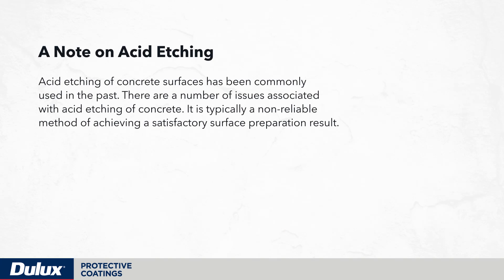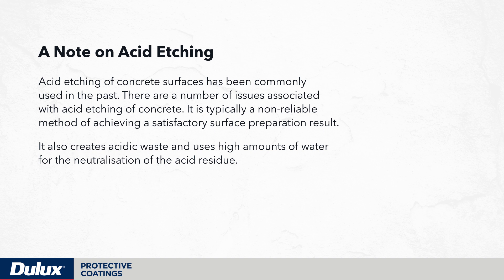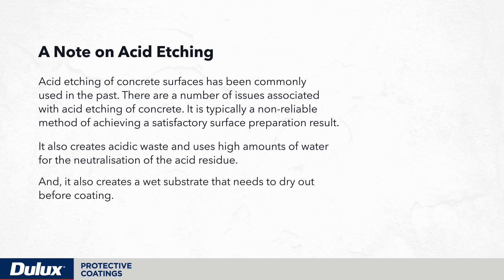Acid etching of concrete surfaces has been commonly used in the past. There are a number of issues associated with acid etching of concrete. It is typically a non-reliable method of achieving a satisfactory surface preparation result. It also creates acidic waste and uses high amounts of water for neutralization of the acid residue, and it creates a wet substrate that needs to dry out before coating.